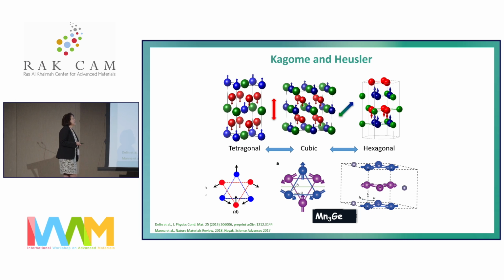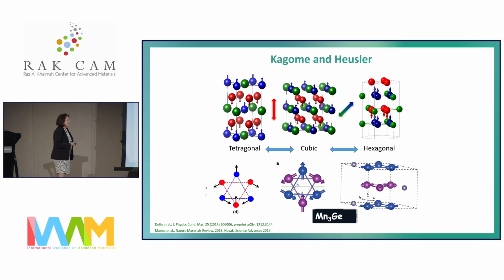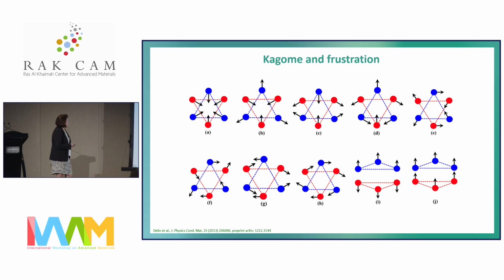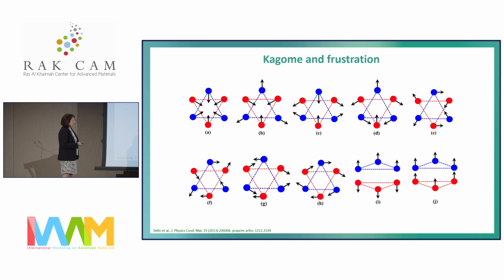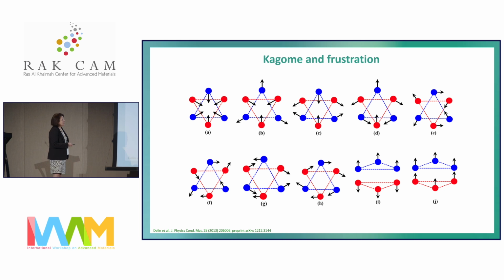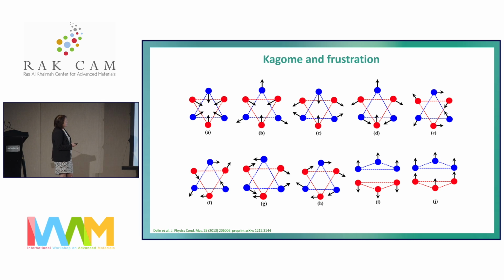So when we recognized that we have a Kagome structure here and potential frustration, and this compound is antiferromagnetic when it's in the hexagonal structure, we were thinking, what could be the magnetic structure? So we calculated at this time with Jürgen Kübler, and he's now 86, still one of my best co-workers, all the potential frustrated lattices in this material, but we checked also the energy of the corresponding ferromagnet, and here the simple antiferromagnet when they are out of plane magnetized, and here are all the possibilities which are allowed, allow a spin frustration in plane. So this was already in 2012, so we were interested, but at this time we didn't see the impact of this material itself,